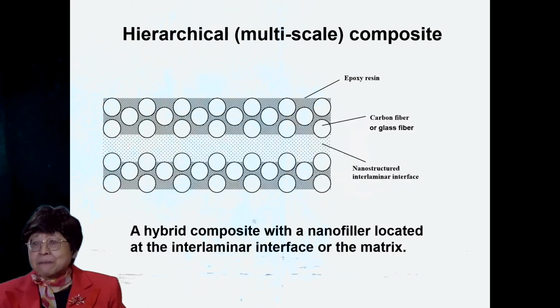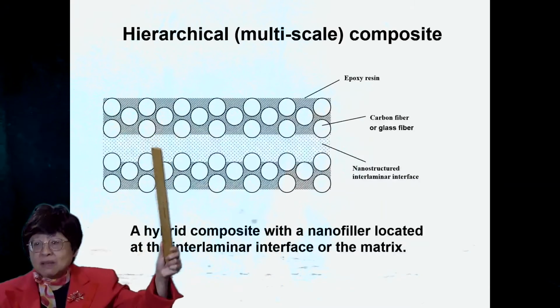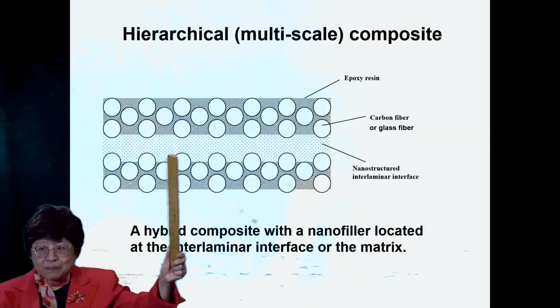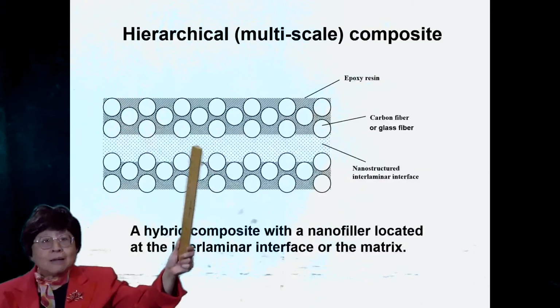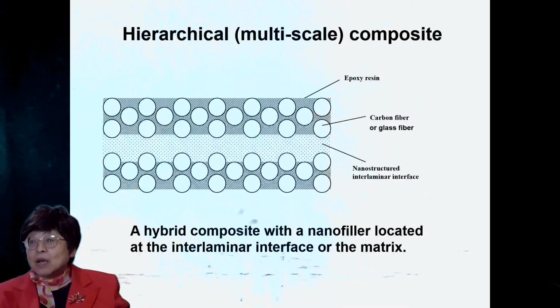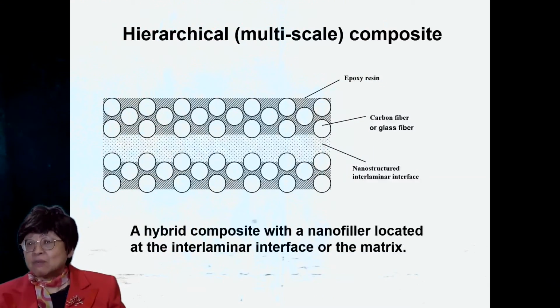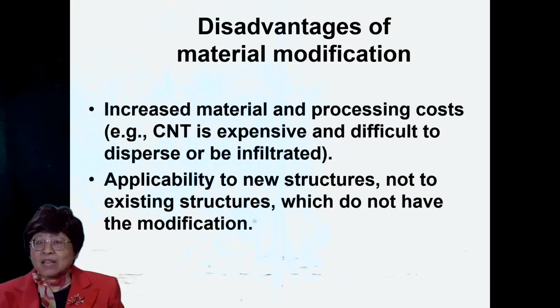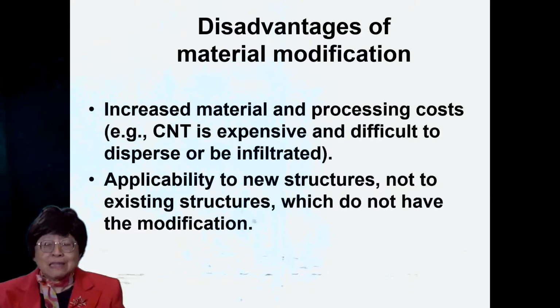On the other hand, if you want to modify the interlaminar interface, which is a small region, you need a nanofiller. So one can put nanotube or other nanofillers such as carbon black here, and that forms a hybrid composite, which is called a hierarchical or multi-scale composite. However, such material modification has disadvantages because of the increased material and processing costs. Also, the applicability to new structures only, not to existing structures, because the existing structures would not have the needed modification.